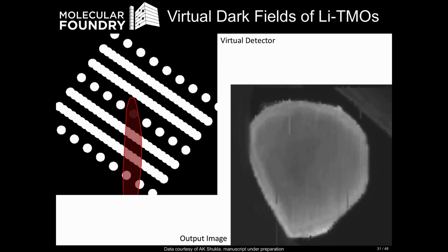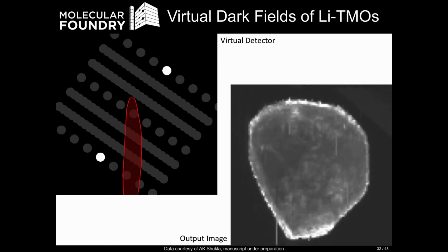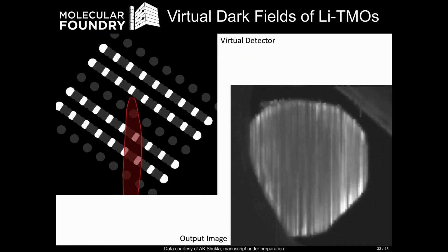But I don't have to use all of the diffracted spots. I can grab just a subset. These two diffraction spots are much more highly excited for the surface structure. So we can pull out the difference between the phases on this entire monolithic particle. It's missing the scale bar, but it's about a micrometer across roughly here. And if I choose every third site in the upper left here, I can form a virtual image corresponding to one of those three variants that I showed previously.